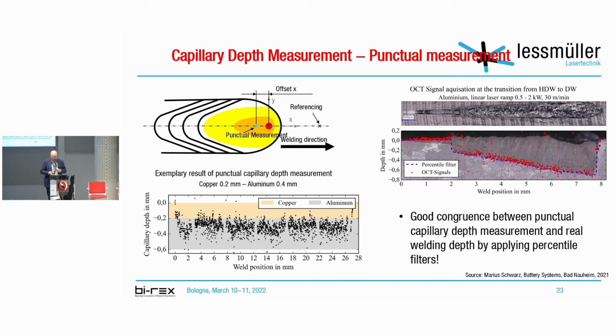And here you can see on the right a weld where the laser power has been ramped up, and below you see the longitudinal cut and etching, and the red points indicating the measurement values, and the blue line which indicates the percentile filter with the algorithms. You see that you really can measure the depth. It's collinear, and you have a congruence between the etching on the material and the OCT measurement.